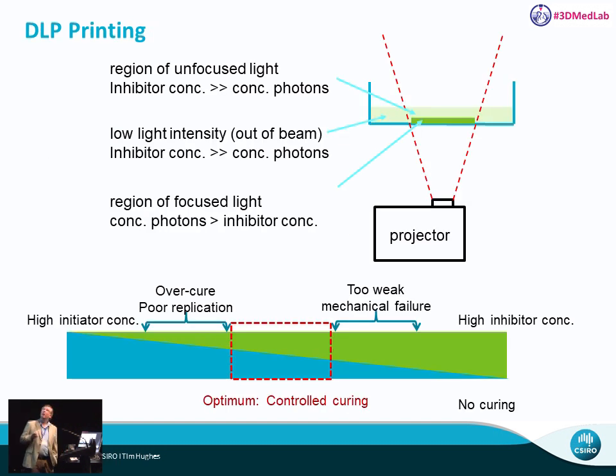So in the DLP printing process, we're using a projector, and the projector basically makes an image of a photomask. So we're doing a photolithography process. And we get curing at the bottom of the vat, where the highest light intensity is. And basically, the projector will change the pattern, and we print another layer on top of it.